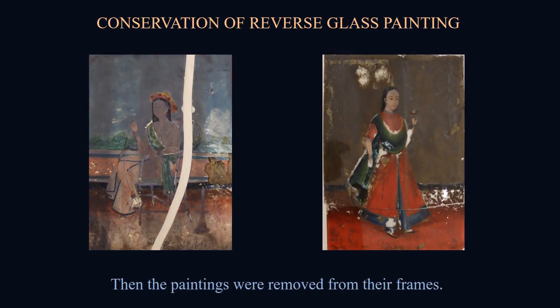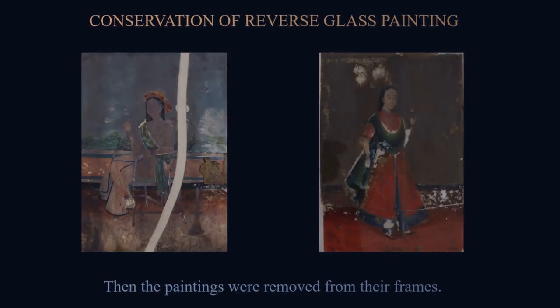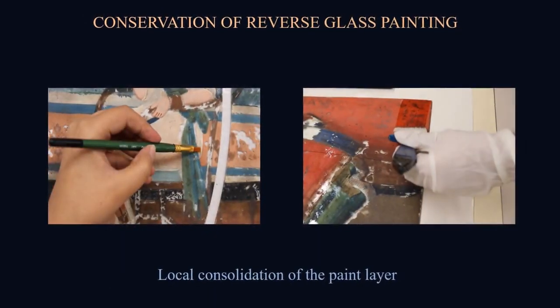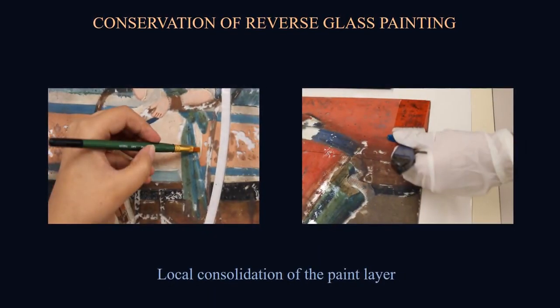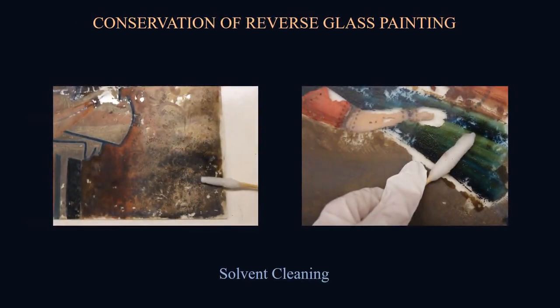Then the paintings were removed from their frames, as the paint layer at the reverse side was to be treated. After removing the paintings from their frames, local consolidation was done using a synthetic adhesive to settle the paint layer and stop further flaking and delamination. In order to keep the paint layer intact, test patches were done and solvent cleaning was undertaken to minimize stains.